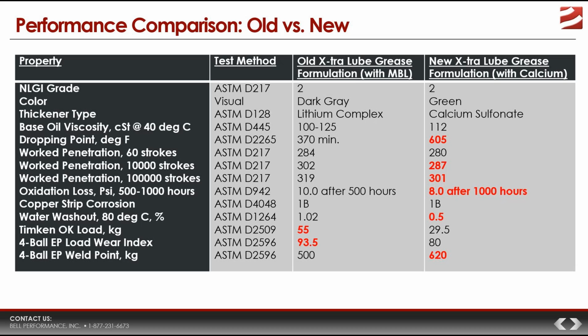Then the 4-ball EP load wear index. Load wear index is a mathematical calculation where, after they have finished running the test, they've gotten the weld points, they've gotten last non-seizure load, which is the load that was previous to before the weld point. They've completed the test. They then take all the scar measurements and plug everything into a mathematical formula. And that gives you a load wear index number.